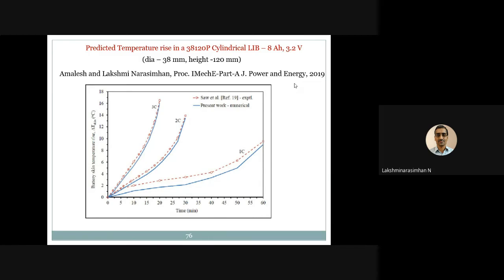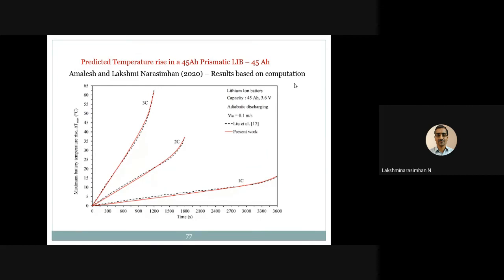Okay, so this is what has been found, and again we made it for a prismatic battery also, and in our publication we used this, and we found that the temperature rise was around even 60 degrees centigrade for this particular battery. Okay, so these are computational results. We have also done some experiments with the prismatic battery arrangement. Okay, that also we have found.